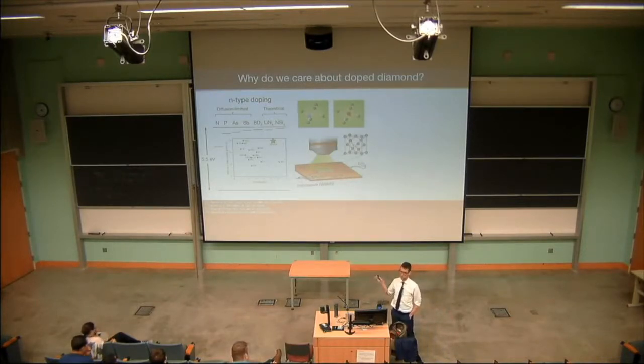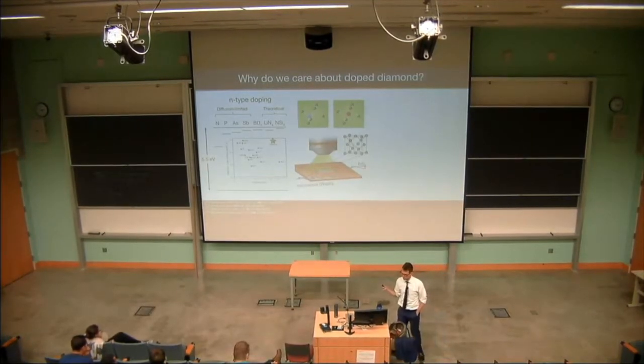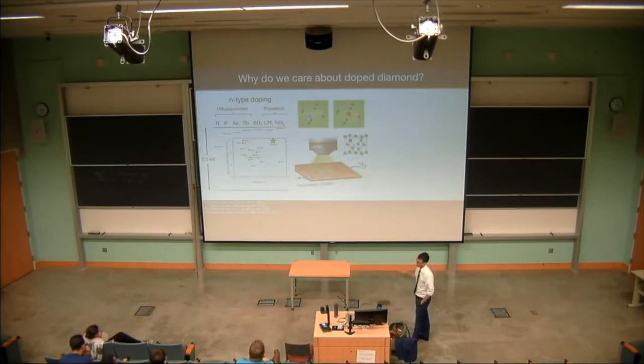And we typically talk about the negatively charged version of this atom. Using the nitrogen vacancy center, groups have been able to do some pretty incredible things, like measure local magnetic fields on a substrate with now nanometer precision, looking only at the luminescence from these nitrogen vacancy centers in diamond. Similarly, this silicon vacancy center is an incredibly popular material due to its very narrow zero phonon line for applications in quantum sensing, in quantum information.